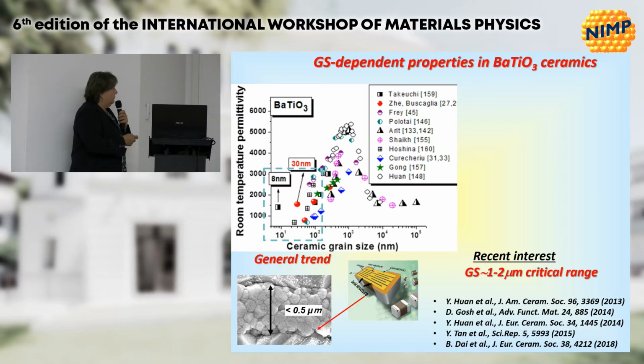So up to 7 years ago, the big interest was focused on this range because it was related to how to preserve a high permittivity level above 1000 when you reduce the physical size of the particles or grains below 100 nanometers. In the last 5 years, maybe, some studies appeared that again focus on this range of the permittivity maximum. And also, for solid solutions, people search if there is a similar maximum when titanium or barium are substituted to some levels. Why the interest in this maximum? Because it enhances permittivity. So if you have a relaxor state in a solid solution that gives you 10,000 or 20,000 permittivity, if you can still increase it by 50%, this would be great.